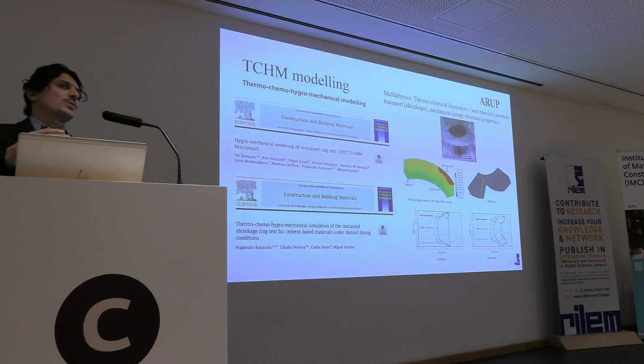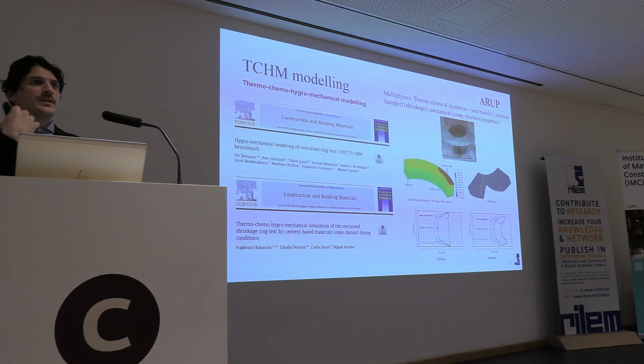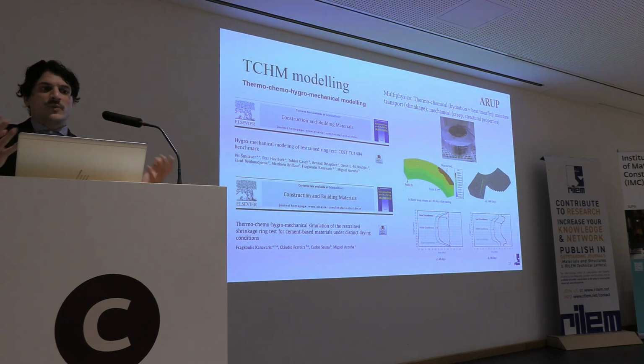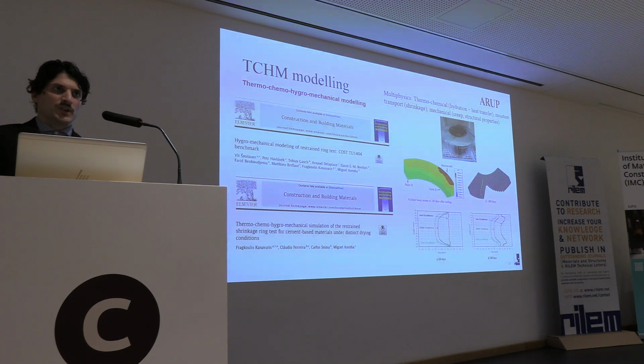And this was quite useful to elucidate some insights on whether shrinkage is relevant in massive concrete structures, or in some structures where shrinkage is being disregarded. For example, we found that the self-restraining effect due to moisture gradient can be quite significant. That cracking is initiated due to the self-restraining effect at surfaces of the concrete, which was previously disregarded. So sometimes when we go on sites, we still see this problem because it has not been properly accounted for.